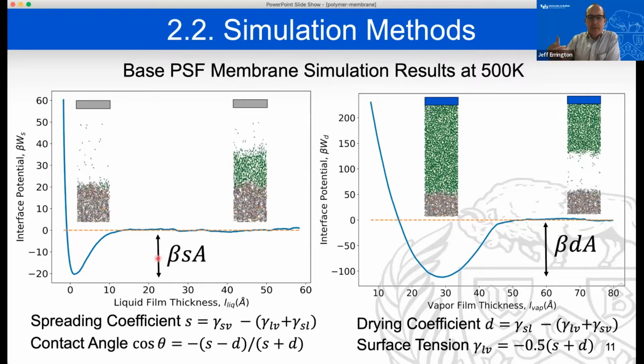From a quantitative perspective, if the system is within this partial wetting regime, then the distance between this plateau region and this minimum region here is related to the spreading coefficient, which is a standard quantity within interfacial thermodynamics. And this spreading coefficient is related to the interfacial tensions between the solid and the vapor phase, the liquid and the vapor phase, and the solid and the liquid phase. So specifically here, this distance is related to beta, so that's 1 over kT times the spreading coefficient. In this case, this is an intensive spreading coefficient, and it's multiplied by the area. In this case, it's the cross-sectional area associated with the surface. Okay, so that is the main output that we get from one of these spreading simulations.